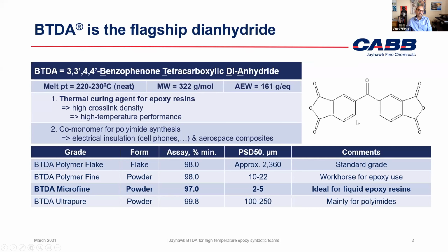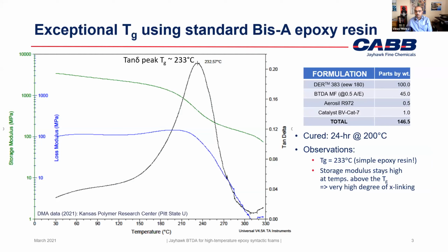The key is that this material gives a very high crosslink density once it is heat cured with epoxy resins, and that high crosslink density translates to high temperature performance, such as Tg, modulus at high temperature, and other mechanical properties. But it is available basically as a fine particle solid powder. And again, if you have questions, please keep sending them. I have two more quick slides. I could possibly save them for later in the discussion, but at least this slide I want to show because when I say high temperature, I want to give people an idea of what we're discussing.